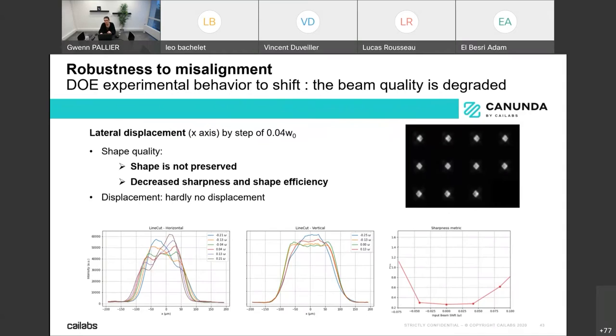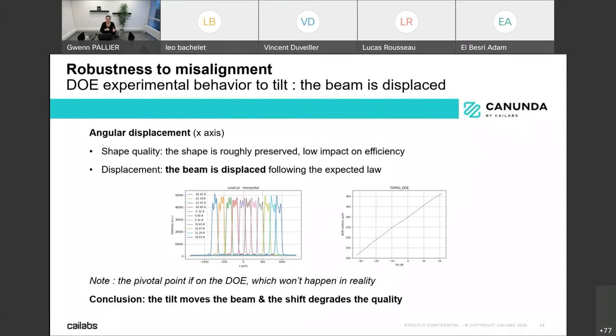And when you are doing some tilt, on the other hand, the beam is actually displaced, but the shape is more or less preserved. The truth is that when we were doing this experiment, we had the pivotal point of the whole experiment on the DOE. It means that we have only shift on the DOE with no tilt, or only tilt on the DOE with no shift. In the real world, you never know where the pivotal point of your laser instabilities is. What does that mean? It means that all the time you will have shift and tilt at the same time, and you will have your beam displaced and the quality degraded.